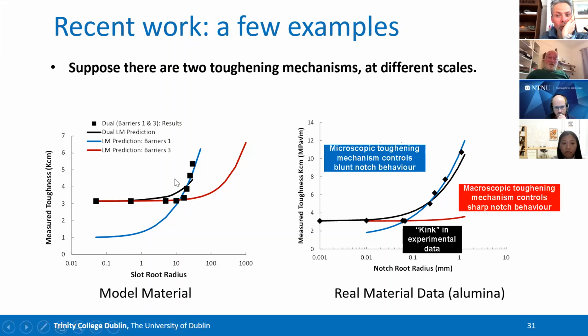And so on the left, we've got the theoretical predictions from those simple models I just showed. But here we've got actual experimental data. And the lesson in this particular case is that for a sharp notch or a crack, behavior is controlled by one mechanism, which is a macroscopic one that operates at quite a large length scale. Whereas when you get to a larger radius, it flips, you get a kink in the data, it goes to the blue line, and you're now predicting it using a microscopic toughening mechanism. So two toughening mechanisms going on in the same material, but they don't control at the same time. One of them controls in some cases, and the other one controls in others. So it's just a way to, again, dig into the mechanism.